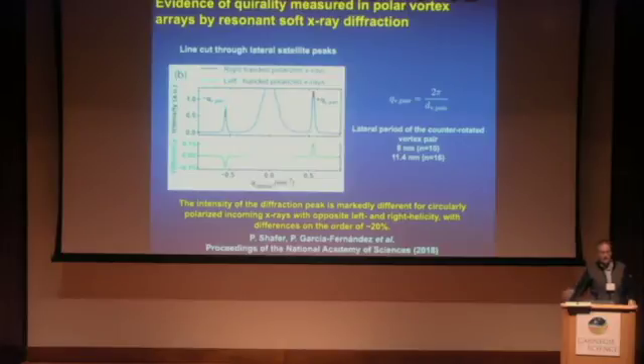I mean, the system wants to close the up-down domains, just forming this kind of closing pattern, and this is just for a single material, no need for two different materials. Of course, this will be metastable, because if you have lead titanate, whoop, everything will tend to polarize in a given direction. But at least you can stabilize them at a metastable level. I think with that we have to move on for interest of time, but we can talk in the coffee break. So thank you very much.